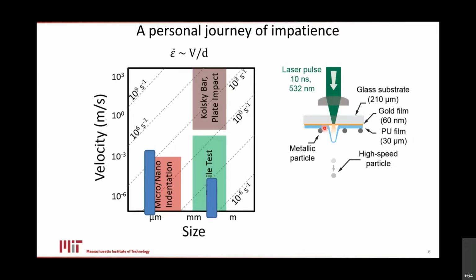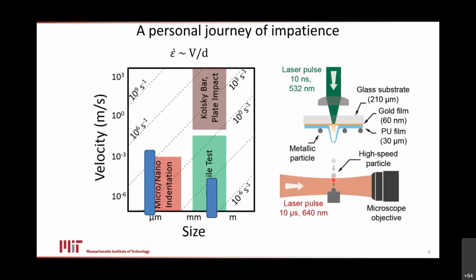That's, of course, a well-known phenomenon that you can ablate a tiny volume of gold with a nanosecond laser pulse. But what these guys had done is they had turned that into a method of doing mechanical work by encapsulating it behind a film of polyurea elastomer, right? So that when you ablate that gold and you get this explosive volume expansion, you're inflating a little balloon here at the nanosecond time scale. And they were using that to launch little particles. So if you characterize a particle, put it underneath that laser, you can now blast it off with that laser. And because they're working on an optics table, they can also time it so that they're able to use a secondary laser as an imaging opportunity so they can take pictures of this thing.